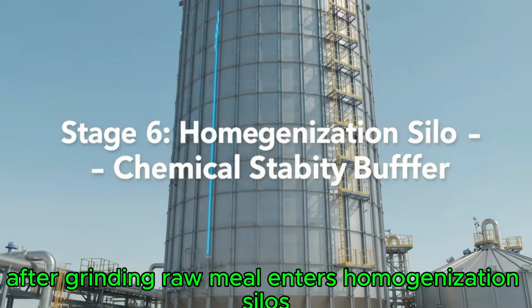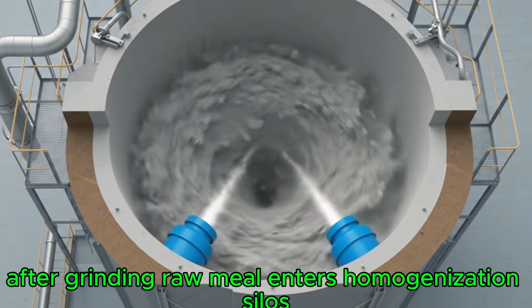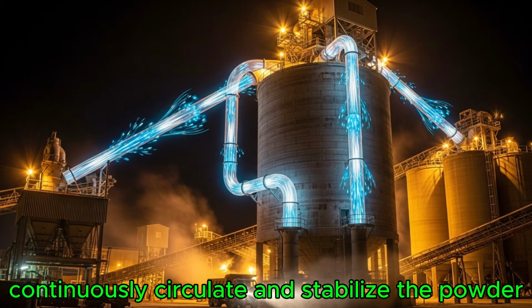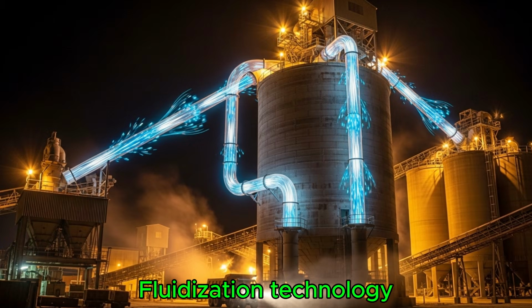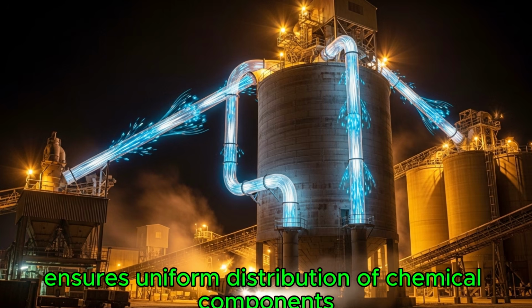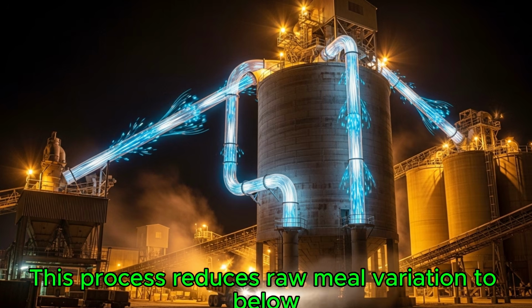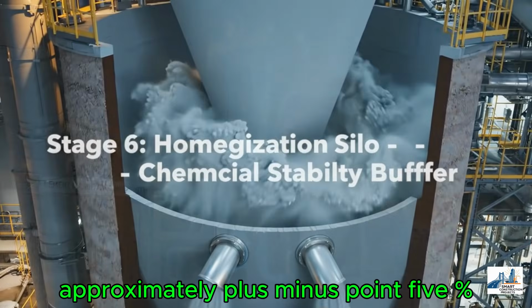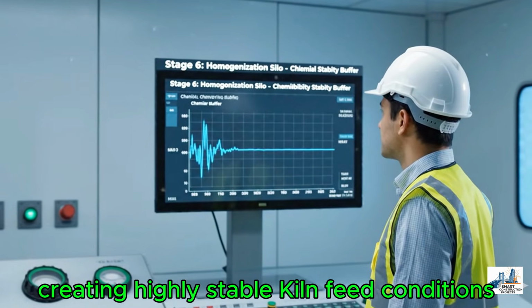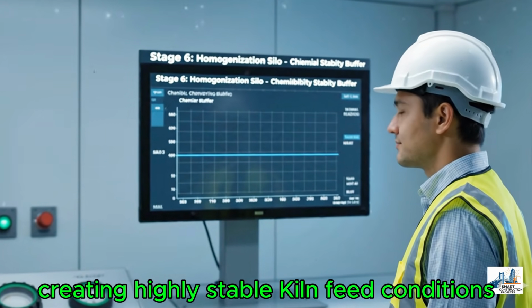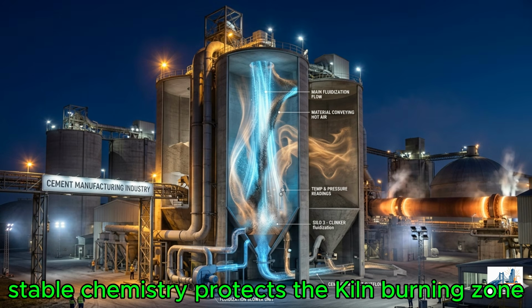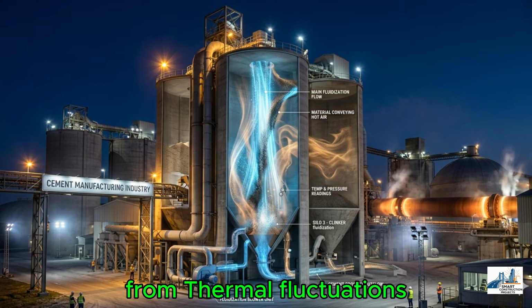After grinding, raw meal enters homogenization silos where compressed air blending systems continuously circulate and stabilize the powder. Fluidization technology ensures uniform distribution of chemical components throughout the silo volume. This process reduces raw meal variation to below approximately plus or minus 0.5%, creating highly stable kiln feed conditions. Stable chemistry protects the kiln burning zone from thermal fluctuations and refractory stress.